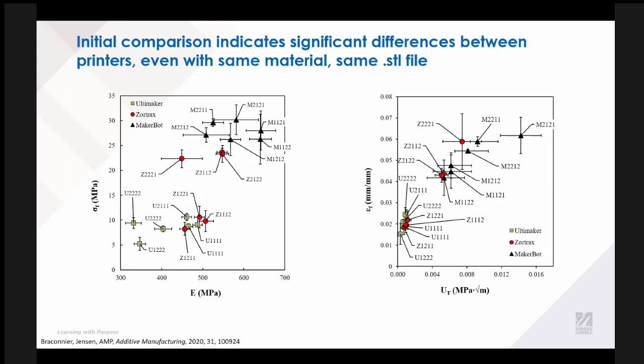So here we have our failure strength and our modulus, and then our strain to failure, and then our toughness. What we're seeing is that for each of these cases, the parameter that was most important was actually what our printer is. You can see that the Ultimaker prints are in this bottom left quadrant. We've got the MakerBot conditions clustered up in the top, and then we've got half of our Zortrax data points here and half here, and that's similar across all the data. And that was really surprising to us.